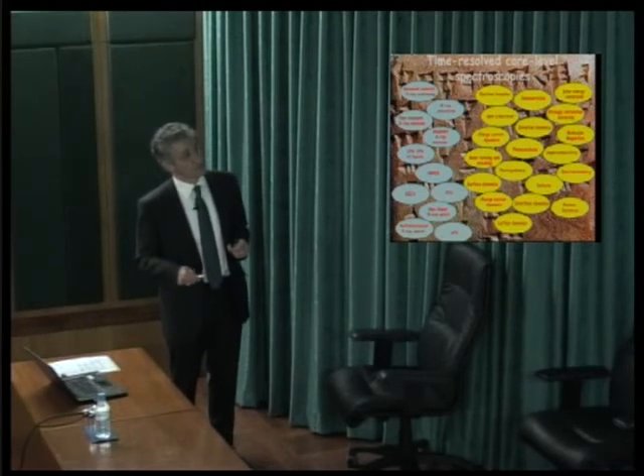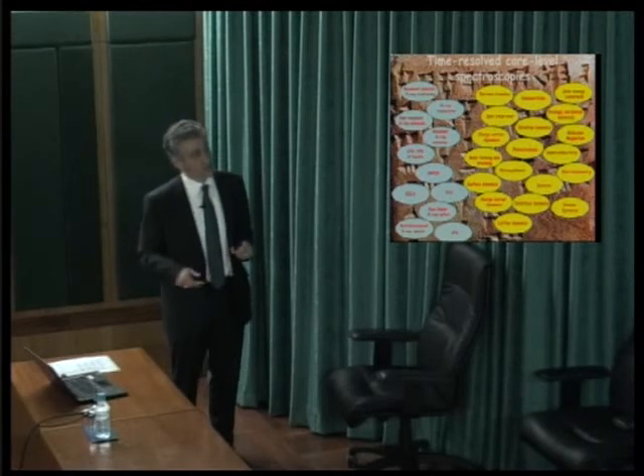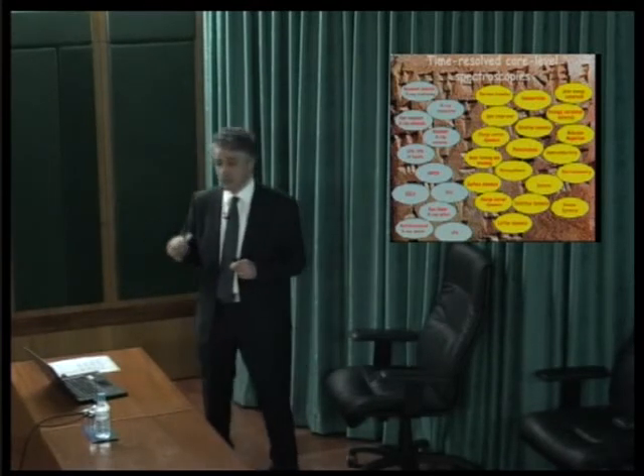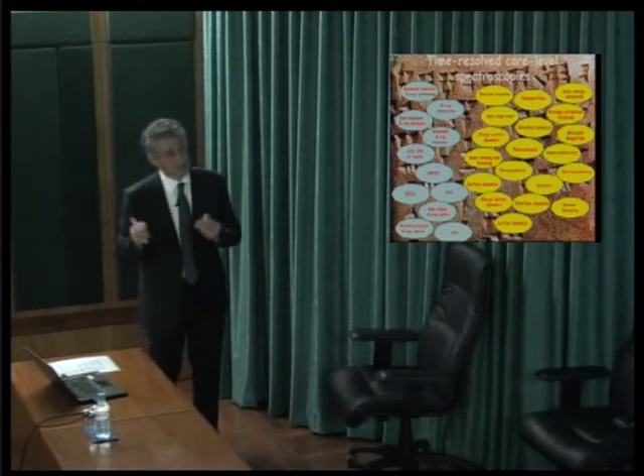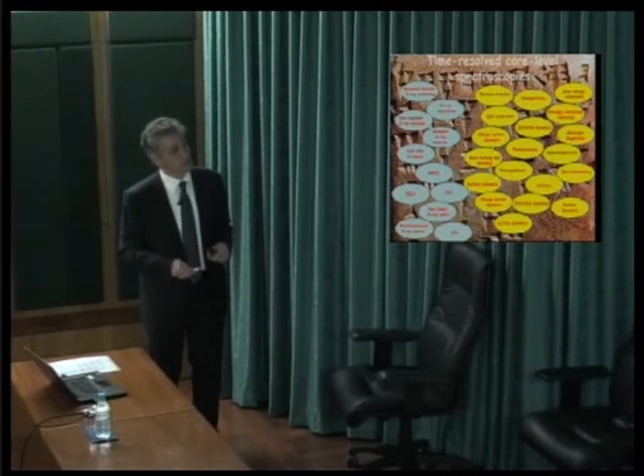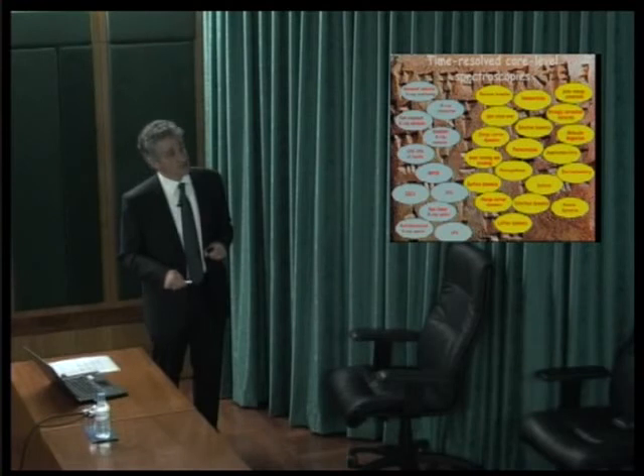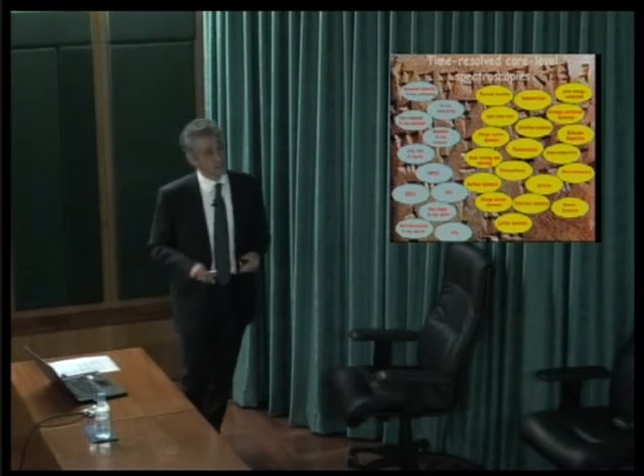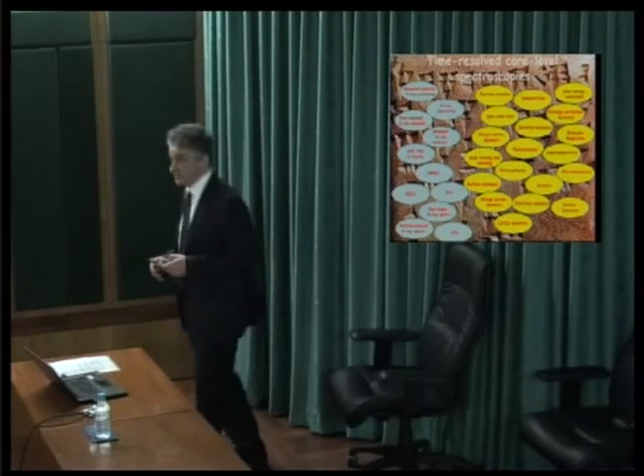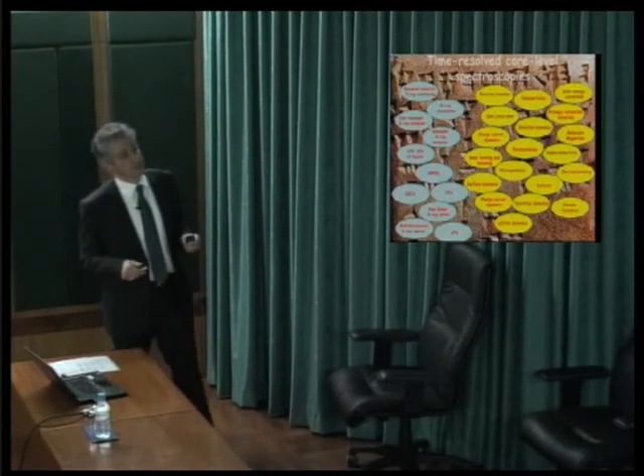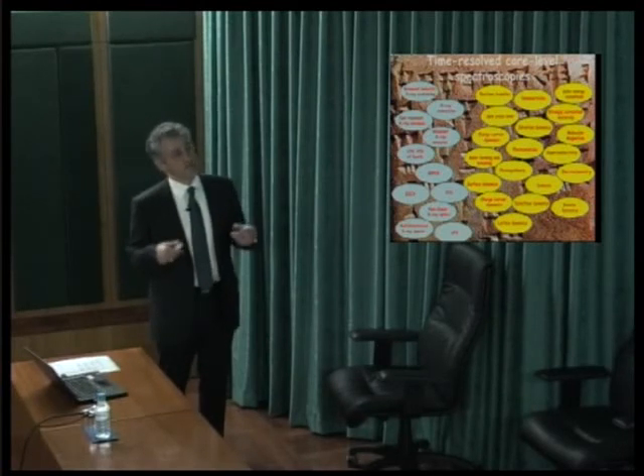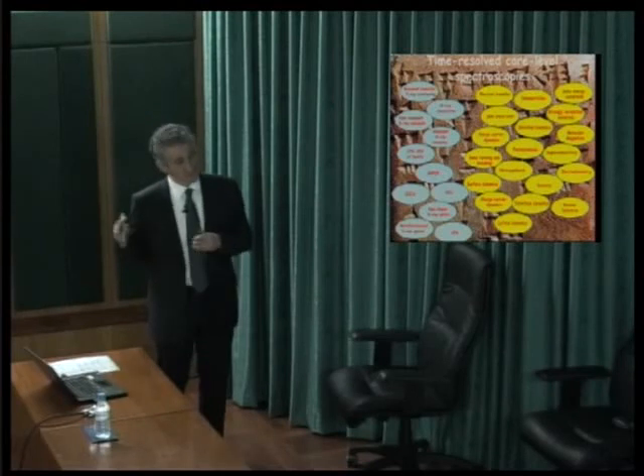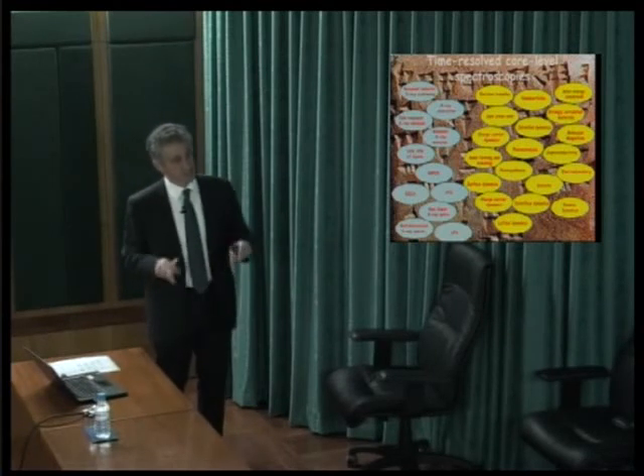I mentioned X-ray absorption. We have results on X-ray resonant emission. I did not mention photoelectron spectroscopy of liquids, which is by no means trivial, because you have to detect electrons and you have to inject them. So you need vacuum, and your liquid is under vacuum, but we manage now to get results on this. Angle-resolved photoemission is another very powerful tool used by condensed matter physicists, and it's basically the sister of RIXS. And so on. And all the domains that are now expanding thanks to the arrival of free electron lasers is just amazing. Now, I want to say that the results I showed you briefly wouldn't have been obtained only with these techniques. In fact, you have to combine also time-resolved optical domain spectroscopies, whether absorption or fluorescence, with all these core-level techniques in order to get the full picture.